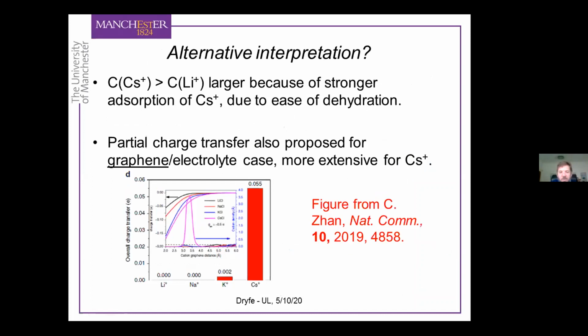There is another interpretation, because we've only considered basically these differences in capacitance due to the difference in size of the ions, but a paper came out last year which reevaluated our data on these specific ion effects and capacitance, and that's this paper here from this American group, which appeared in Nature Communications. They basically explained or rationalized these differences in capacitance for the different alkali metals, in their case I think they were using graphene as the electrode material rather than graphite, as being partly due to the things that we've essentially talked about, partly due to different adsorption of the ion, which comes from different ease of dehydration.